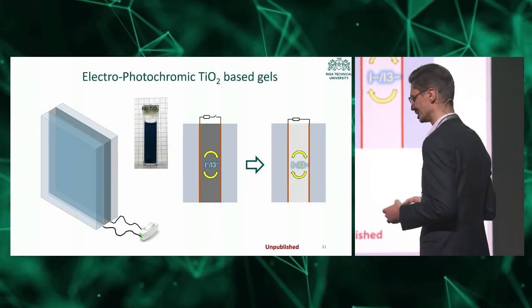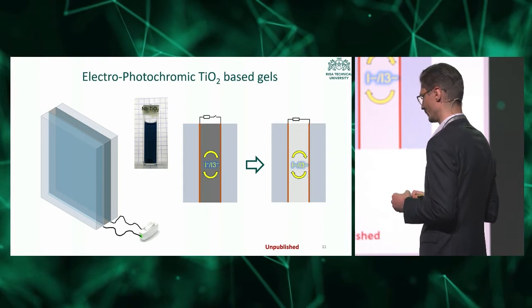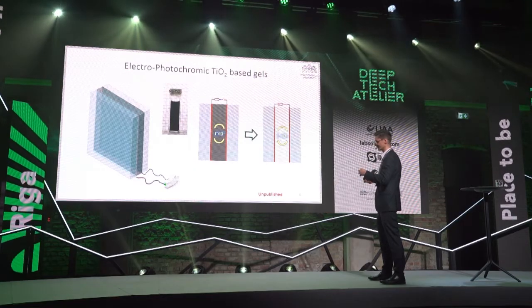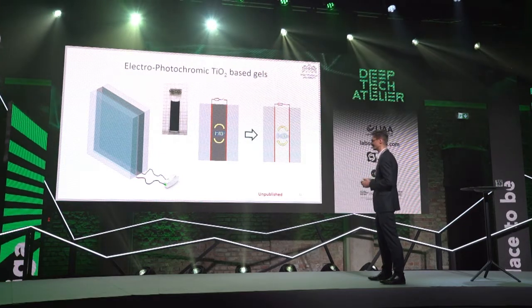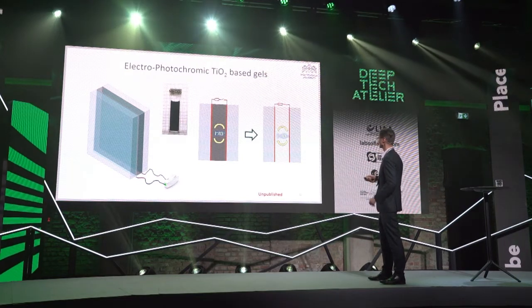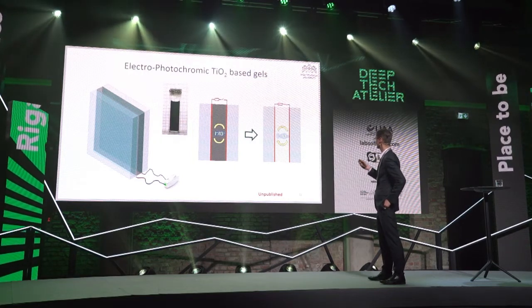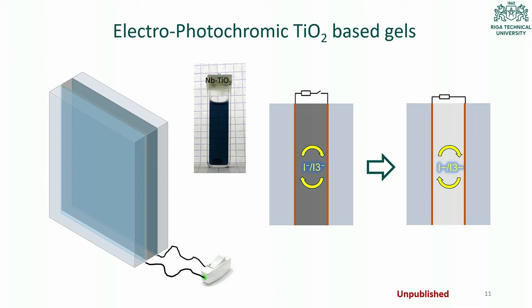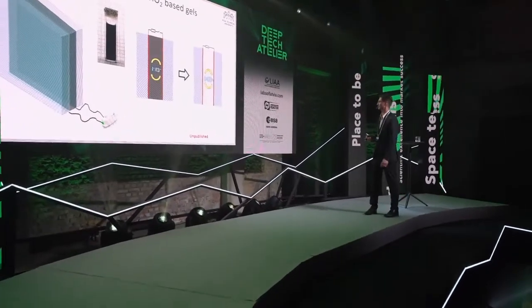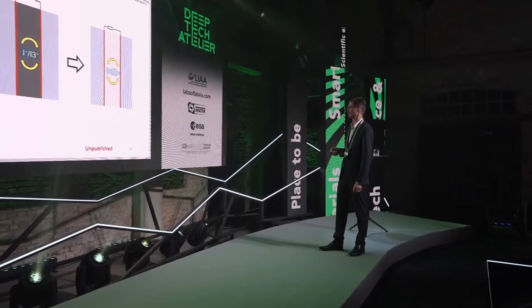We also developed an electrophotochromic device. This is our next step. Without electrodes, we can't switch off the color change, because the color changes when the light is irradiating, but we want to turn it transparent at some point. So we made such a device. There is a gel layer with niobium doped titanium dioxide particles between conductive transparent electrodes, and in the system there is also a redox mediator. When the electric circuit is open, it becomes dark, and when you close the electric circuit, the mediator at some potential is reduced, turning it back to the initial position, and in such a way the gel layer gets transparent again. So this is the device we have developed so far.